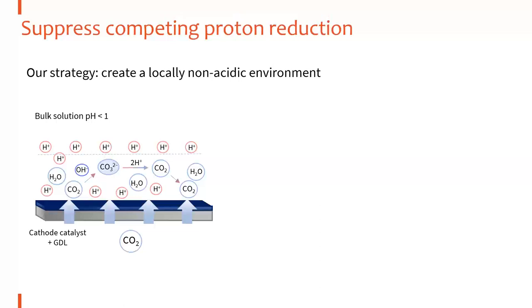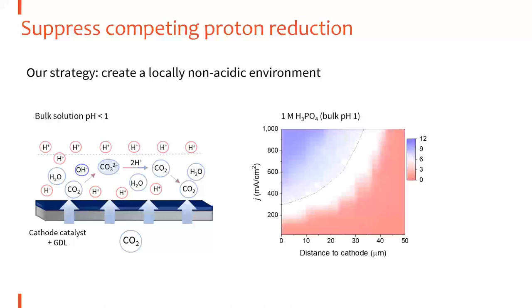The protons are not able to reach the surface of the catalyst to be consumed. That means the local environment is proton poor, while the bulk condition is proton rich. So we have created a local environment with high pH, while the bulk environment is low pH.